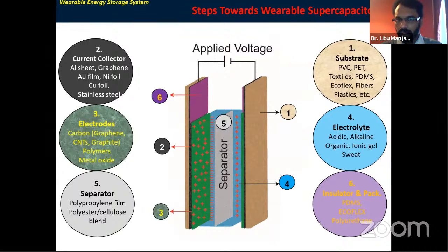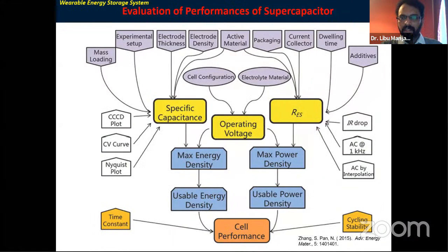And then if you apply a potential between these two, as I mentioned, there are charges stored on the surface. And this is the important point where you want to evaluate the performance of the supercapacitor. So in the yellow color, these are the major parameters: specific capacitance, operating voltage, equivalent series resistance. Specific capacitance means how much capacitance is stored in this device. You can measure this by using charging, discharging. There are different tools, and also electrochemical impedance spectroscopic analysis, or CV analysis. CV means cyclic voltammetric analysis. You can measure the specific capacitance.